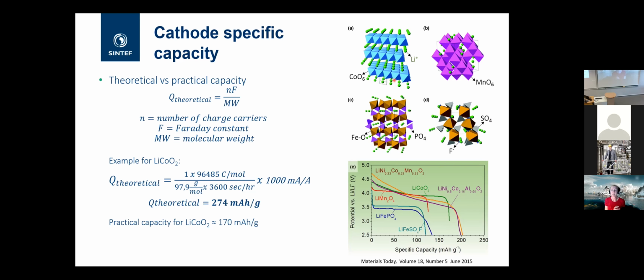When you start taking these lithium ions out of the structure, it starts changing, and you get phase changes in there. If you take out more than about 55% of the lithium in the lithium cobalt oxide, the structure starts collapsing, and it goes through irreversible phase changes. And then you can no longer get the lithium back into the structure. So that's why you're not able to utilize all the theoretical capacity in a material.